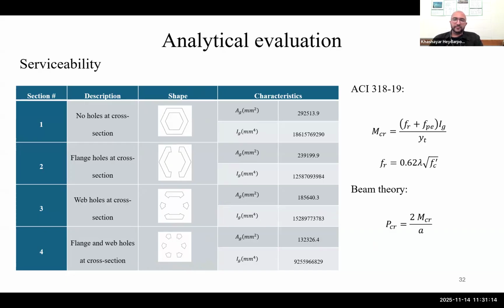section for analytical evaluation. The main design provision for GFRP reinforced concrete structures is ACI 440.1R-15 and also other ACI 440 specifications. However, pre-stressing is not included in this code. And as it was observed from the tests that pre-stressing significantly affected the cracking capacity of the structure, it was decided to use the formulation in ACI 318-19 or the recently published ACI 318-25 for the analytical part.